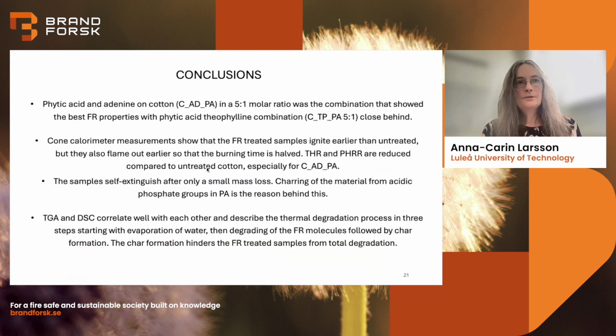We can draw some conclusions from this study: phytic acid and adenine on cotton, in a 5:1 molar ratio, show the best flame retardant properties, and theophylline in the same molar ratio was close behind.